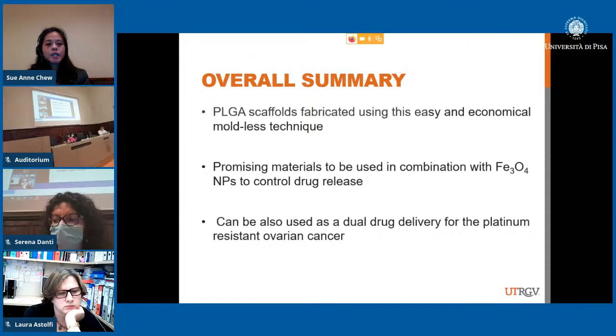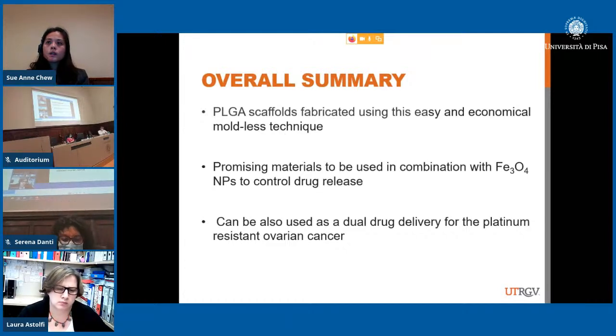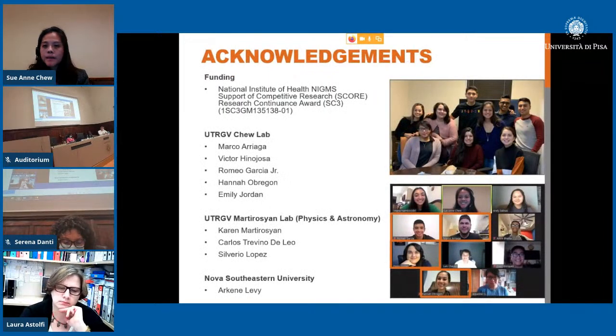So just an overall summary, the PLGA scaffold fabricated with this easy and economic moldless technique was tested in this project. It can be a promising material that can be used in combination with iron oxide nanoparticles to control the release rate, and in turn control cell viability, or how many cells die. And we also can use it as a dual delivery system. So we've used it for the metformin and Y15 combination. We are looking to also use it for our minocycline and temozolomide treatment for glioblastoma.